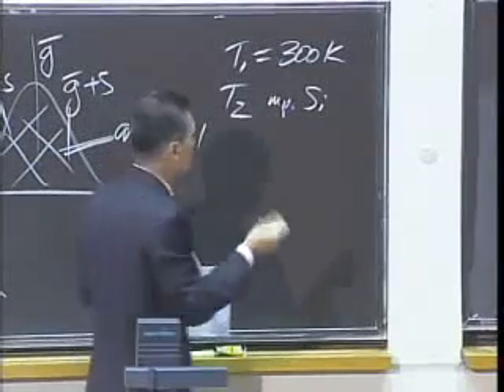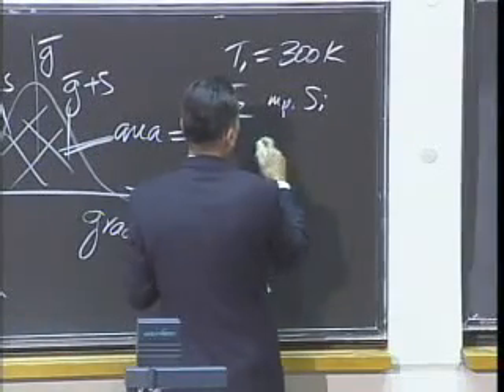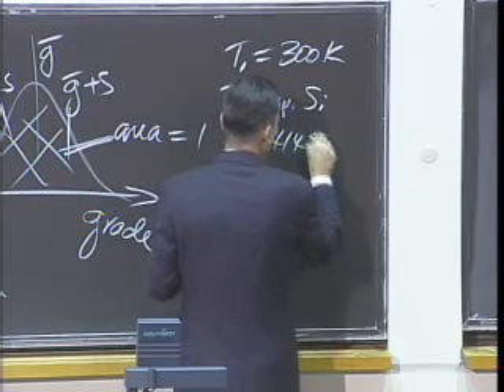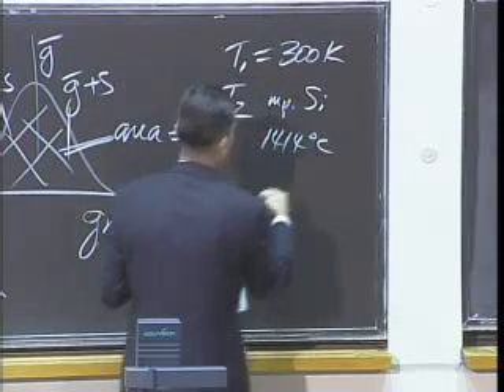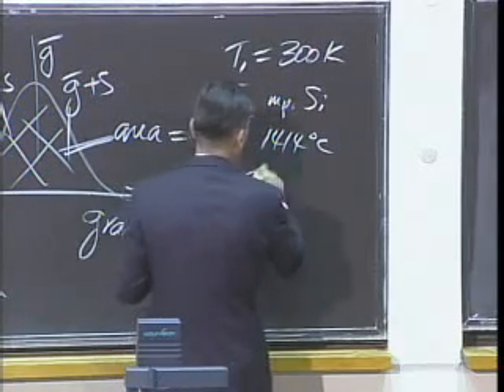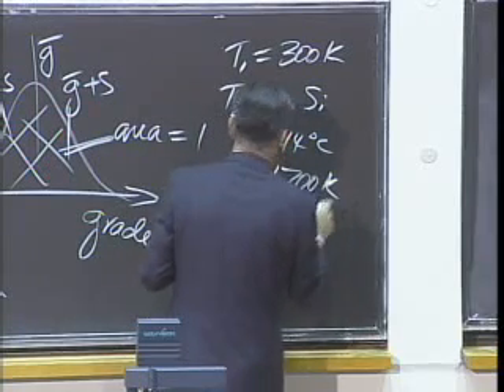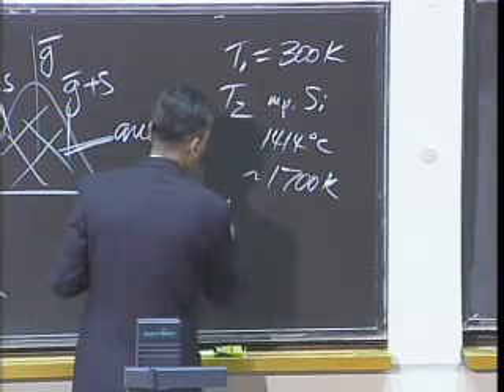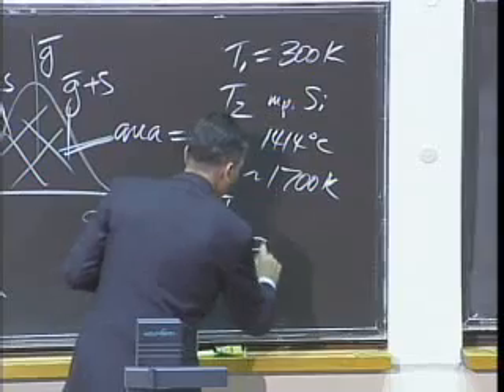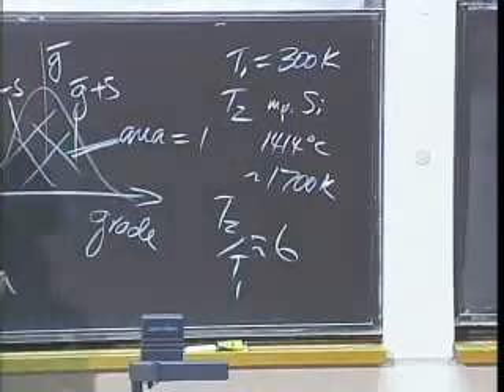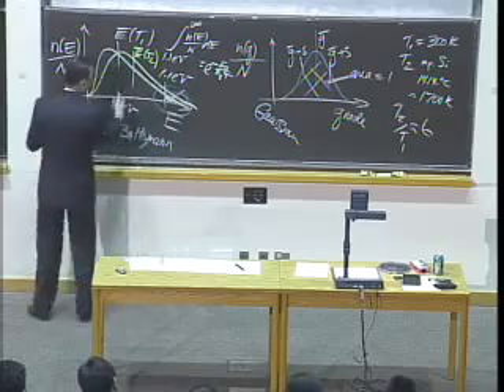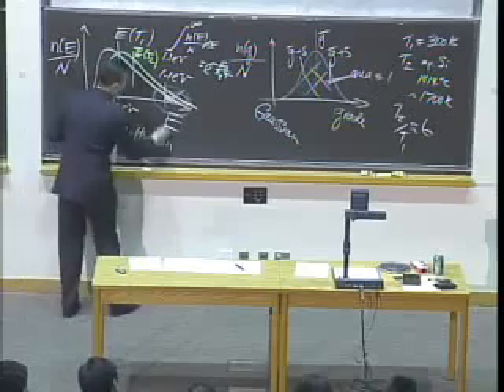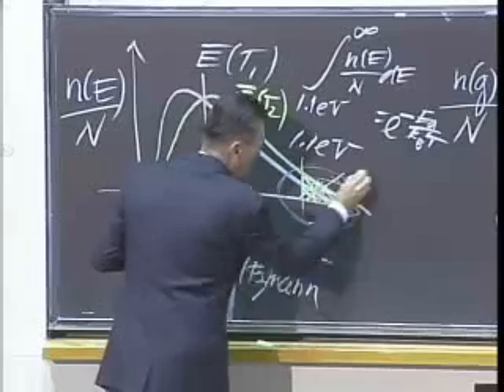So it'd be like ice at 0 degrees C. The melting point of silicon is 1414 degrees C. So add 273 to it and get about 1700 Kelvin. So what's the ratio? T2 to T1 is on the order of about 6. So this thing shifts by a factor of 6. Let's look at what happens in here.